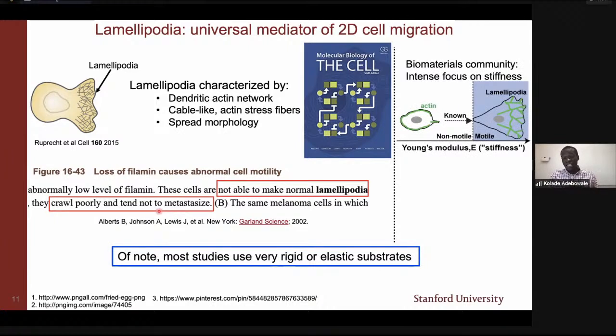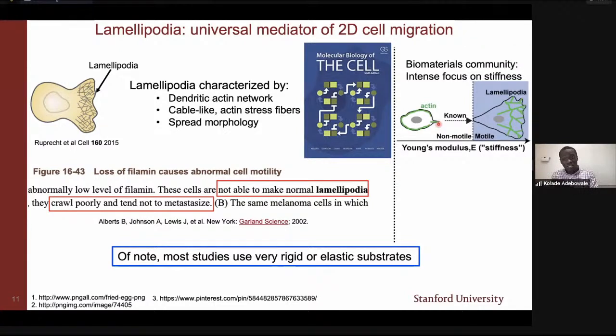Over the last several decades, there's been intense focus in the biomaterials community to try to understand how differences in Young's modulus can impact cell migration. What's been found is that if cells are on compliant substrates, the cells are very rounded and non-motile, shown in this white region. But if those same cells are on more rigid substrates, the cells can become motile, shown in this light blue region, and associated with this transformation is a formation of Lamellipodia structures at the front of the cell that's migrating and a very spread morphology. Of note, however, many of these studies have previously utilized substrates that are very rigid or purely elastic.